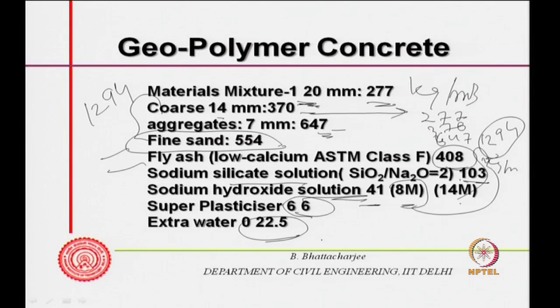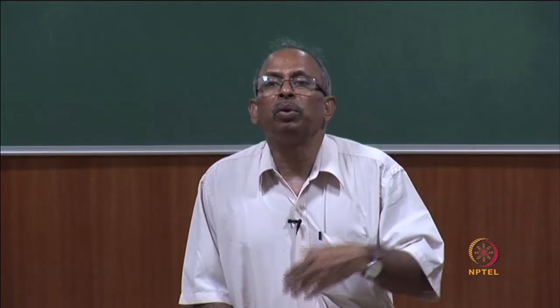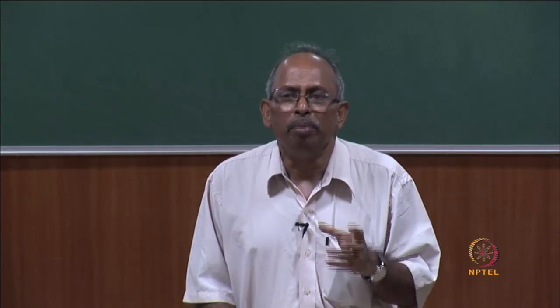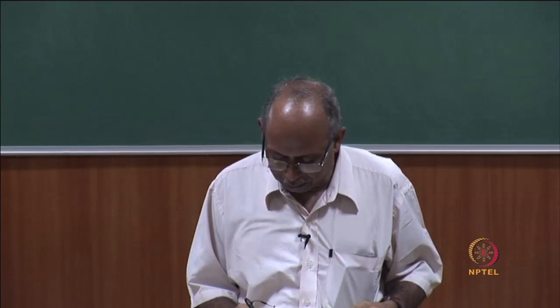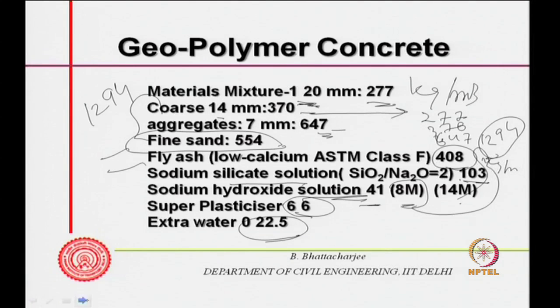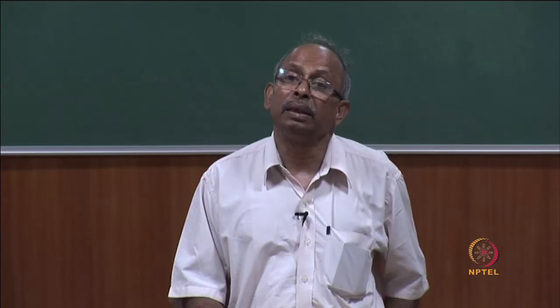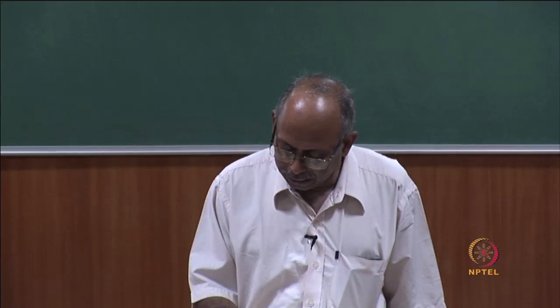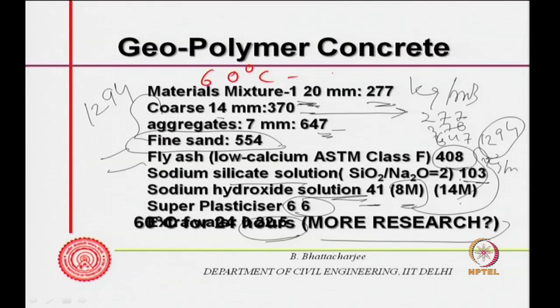So, what are you using? You are using fly ash, sodium silicate, sodium hydroxide, and of course, rest all is like concrete only. And then you make this concrete with 60 degrees centigrade curing temperature. That is the only problem that is there. Curing temperature is 60 degrees centigrade, and that is actually the problem.